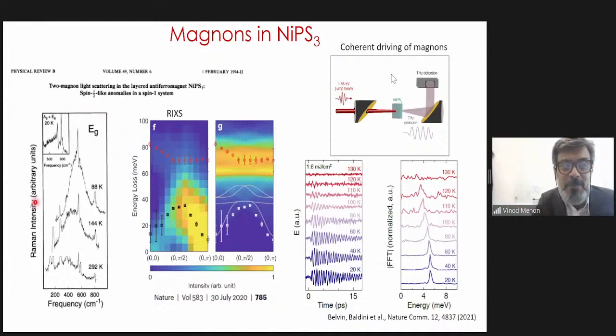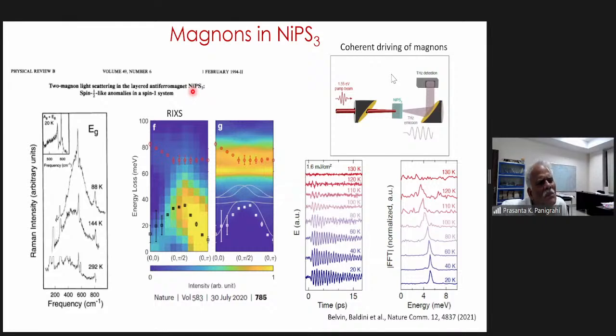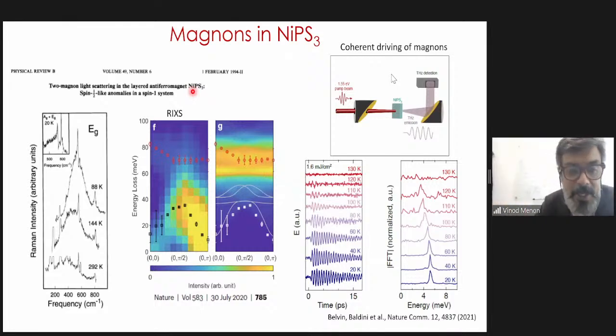Well, the main reason I put this paper up was that this was one of the first studies of this 2 Magnon-like scattering that happens in these systems. So this whole class of materials like nickel phosphorus, manganese phosphorus, they all have this Magnon sideband, where the electronic excitations couple to the Magnons, and you will see that this Magnon sideband is in this case about 500 inverse centimeter or 600 inverse centimeter. The purpose of this paper was more about showing the presence of these 2 Magnon sidebands with Raman scattering. And then they identified this as this particular transition.